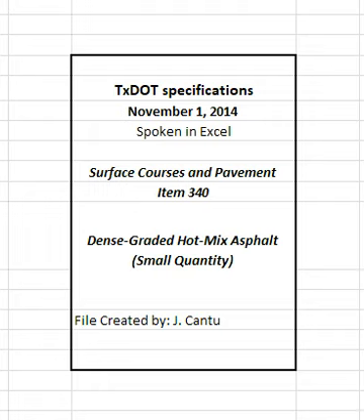Remove substantially all materials before use that are not part of the shingle, such as wood, paper, metal, plastic, and felt paper. Determine the deleterious content of RAS material for mixture design purposes in accordance with Tex-217-F, Part III. Do not use RAS if deleterious materials are more than 0.5% of the stockpiled RAS unless otherwise approved. Submit a sample for approval before submitting the mixture design. The department will perform the testing for deleterious material of RAS to determine specification compliance.